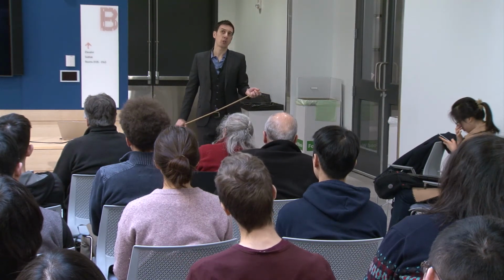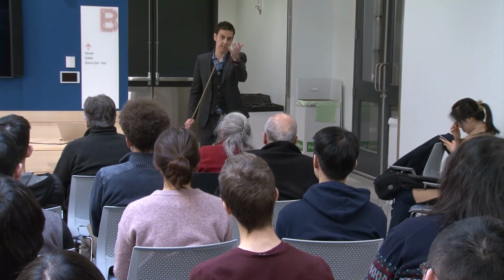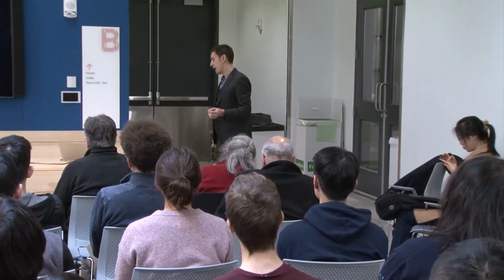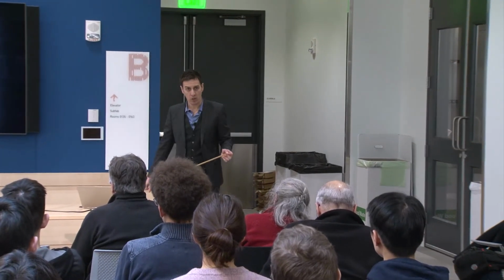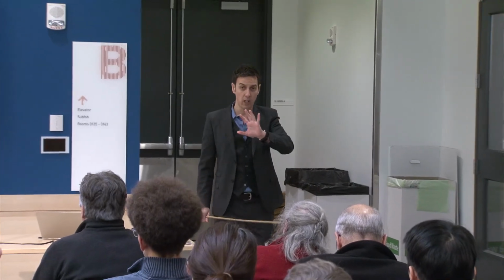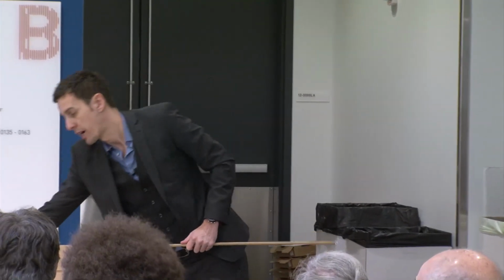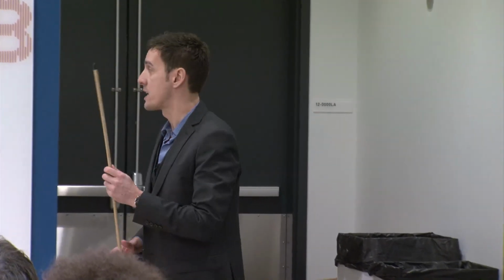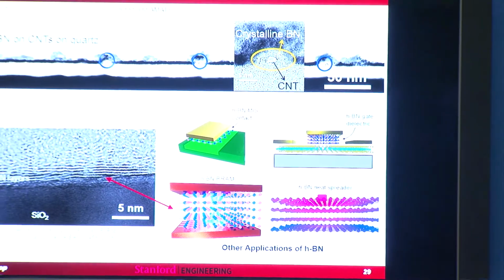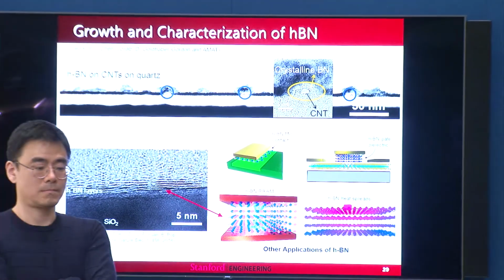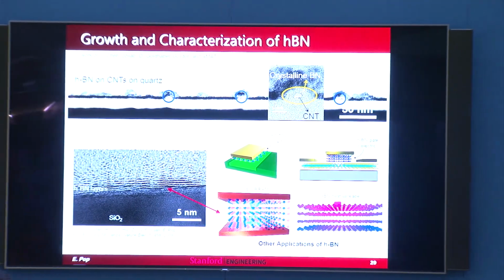Yes, HBN is the simple, the obvious answer there. You're absolutely right. HBN has thermal conductivity comparable to copper, right? But it's an insulator, so I love it for back end of the line kind of heat dissipation. If you want something that has a band gap of about 5.5 eV, so it's a pretty good insulator, but has the thermal conductivity of copper, look no further than HBN. The only way to do better is diamond, right? And diamond's got its own problems, but we're also looking at diamond a little bit with collaborators.